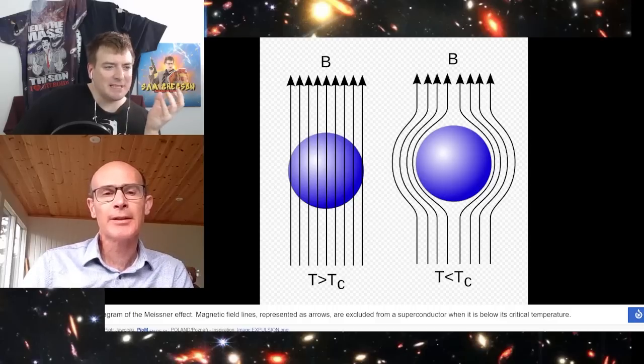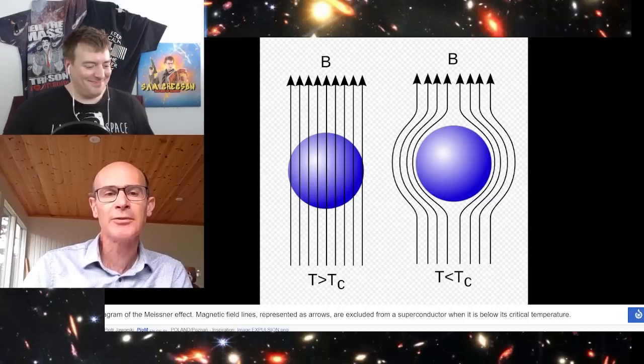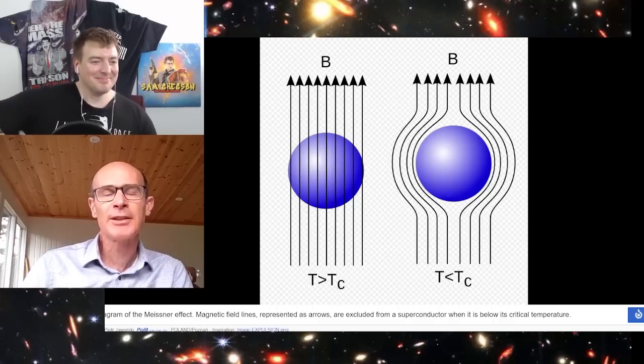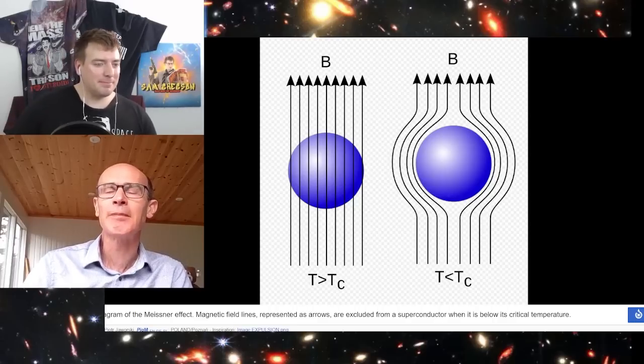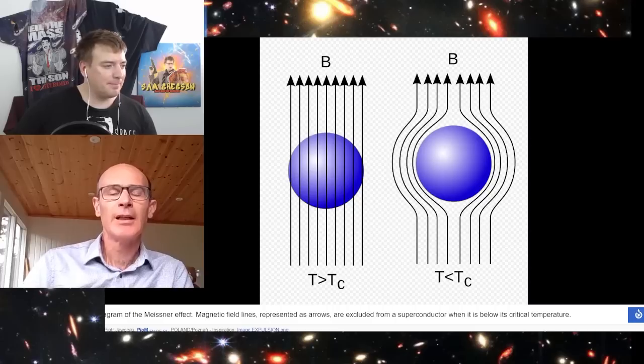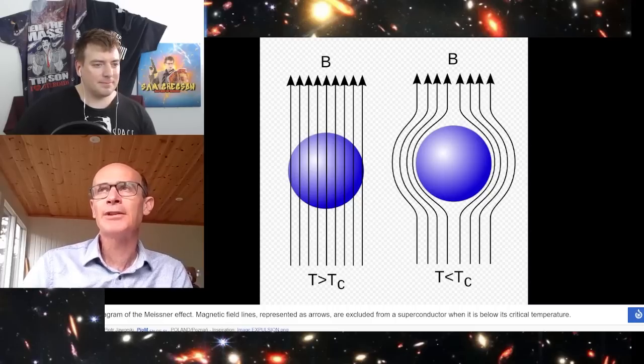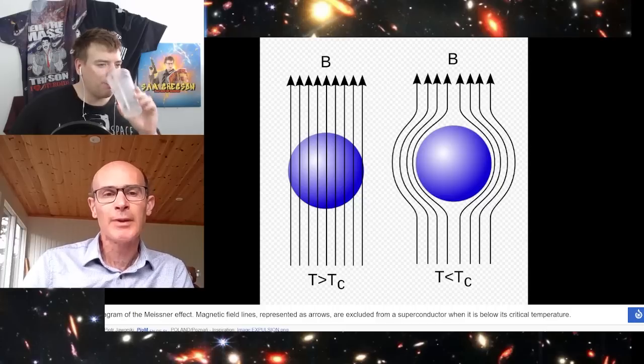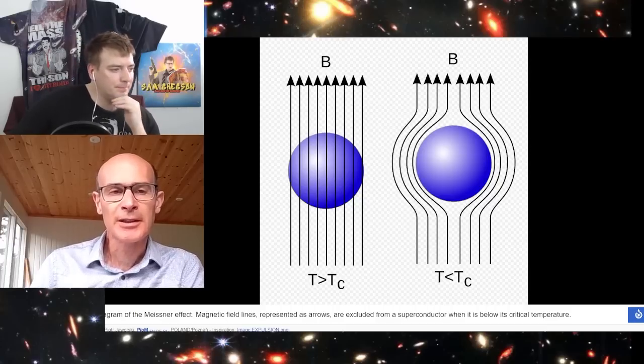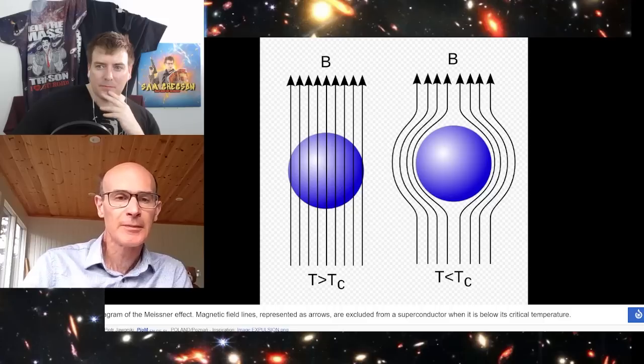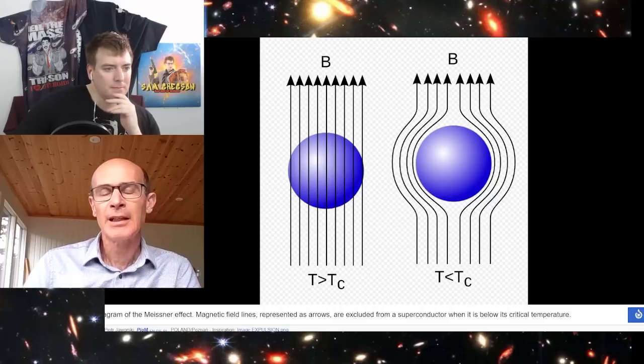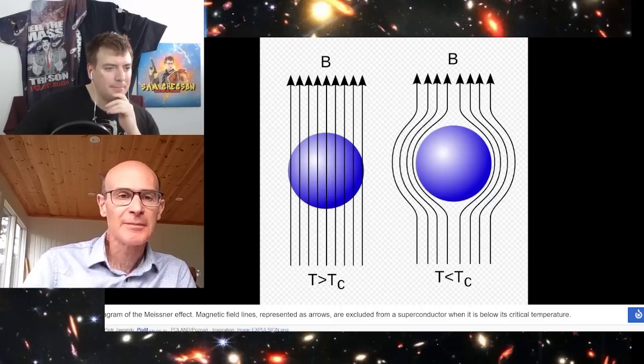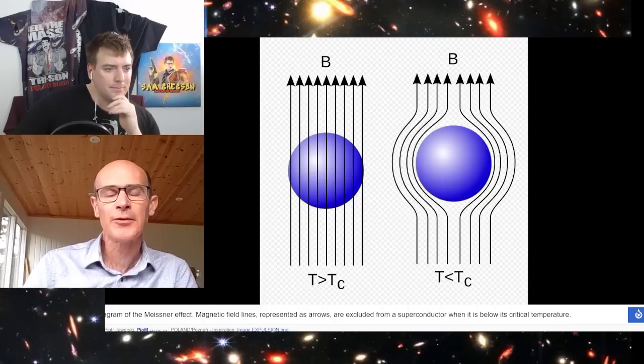So it's sort of tantalizing, but not enough. Coincidentally, it seems to be the temperature that's the maximum for their measurement, the maximum temperature they could reach. Turns out to be the TC. So they should measure well above that temperature. If you heat these levitating samples well above this proposed superconducting transition temperature of about 120 degrees C, do they stop levitating at that point? It would be sort of a partial test.